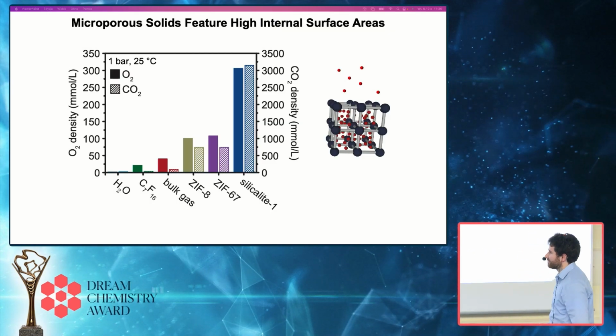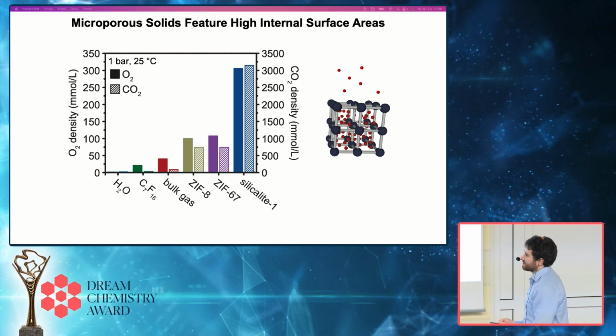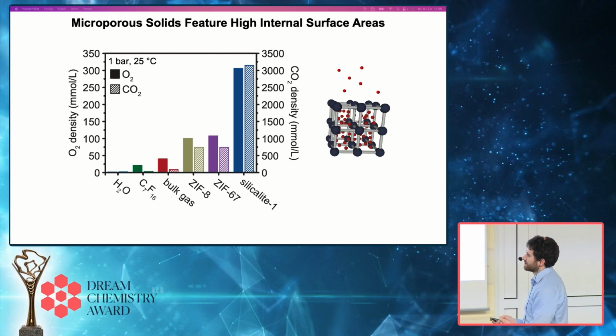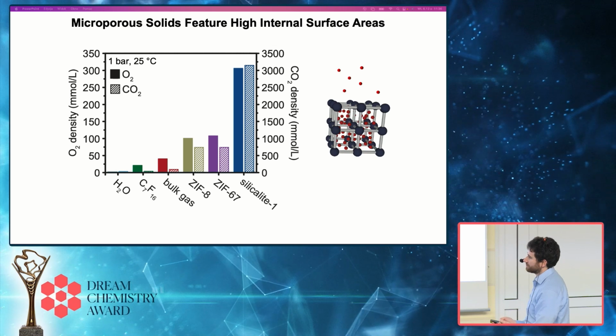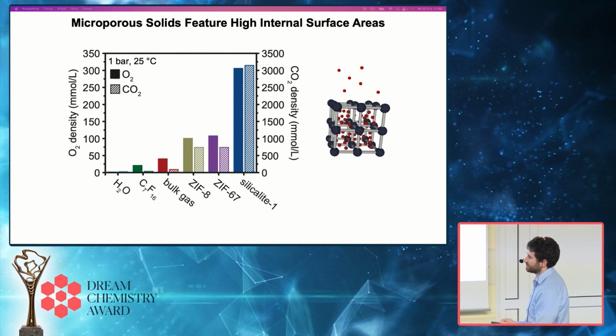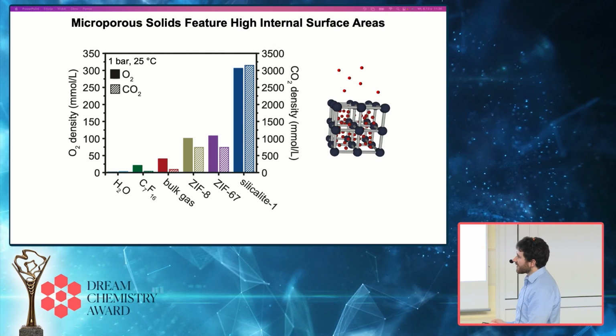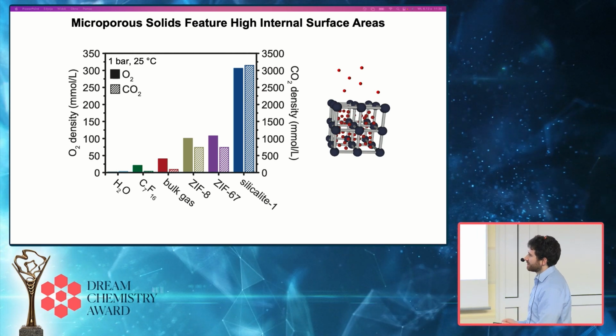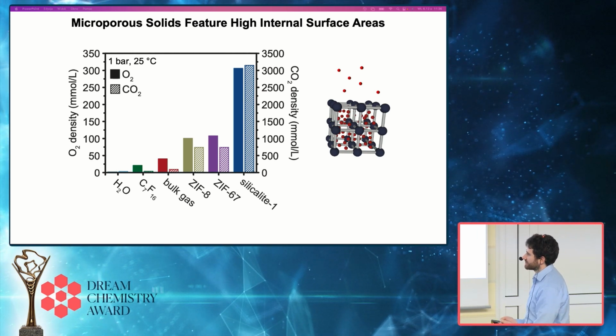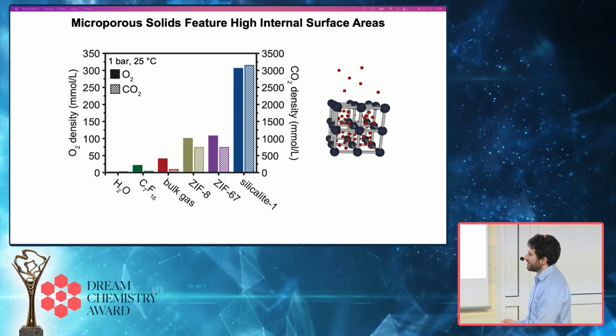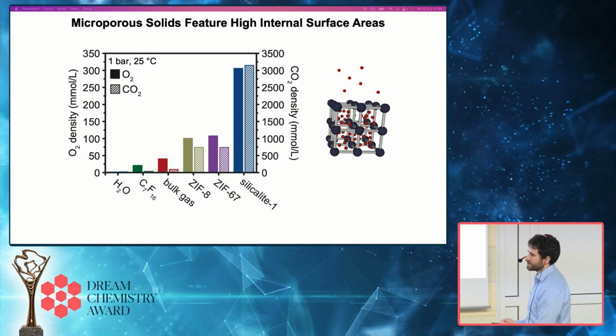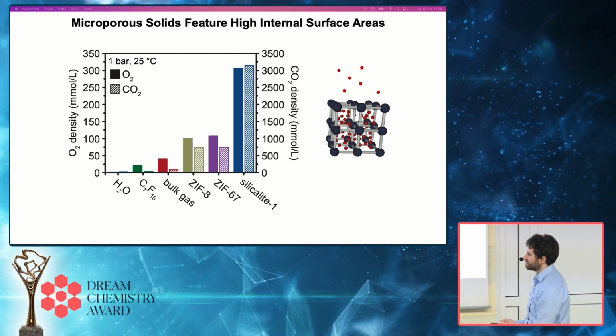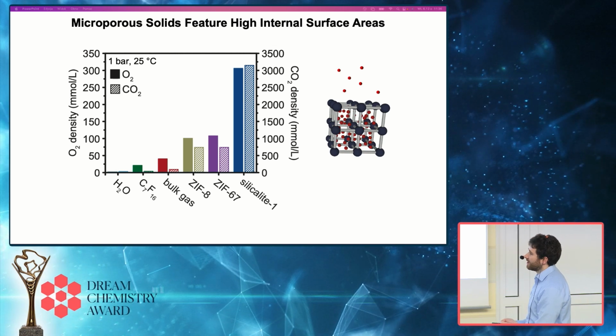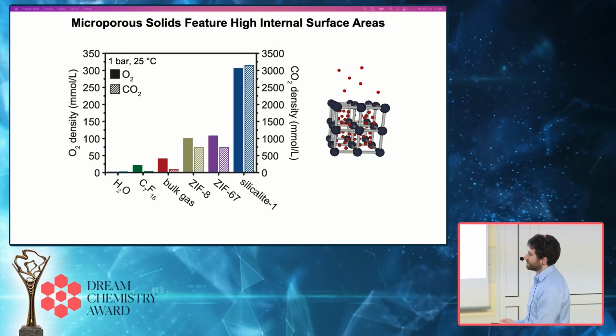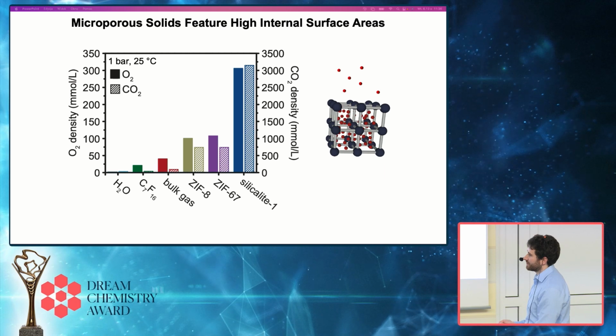To be a bit more quantitative about this, this is a comparison of the density of oxygen present within a porous material, including the amount of space taken up by the porous material itself, at 1 bar and ambient temperature on the left side. On the right side is the density of carbon dioxide for 2 run-of-the-mill representative metal organic frameworks and 1 zeolite, which I'll talk a bit more about in a second, compared to the bulk gas density, perfluorocarbon liquid, and water.